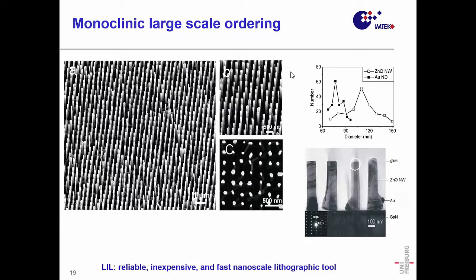And then what you might see, and you see it here in image C, is that zinc oxide is growing hexagonal. That means it has a C-axis growth, and of course not each of these pillars, nanowires, is perfect in shape. Not each of them has a real hexagon, there are variations from that. And depending on whether you go for VS or VLS growth, you might also end up with a deviation from the former size of your catalyst. So you see they are normally bigger than your catalyst pattern was, but you can do that on a large scale. So just to give you a glimpse, you can do that, and now you have a tool to actually make devices out of that.